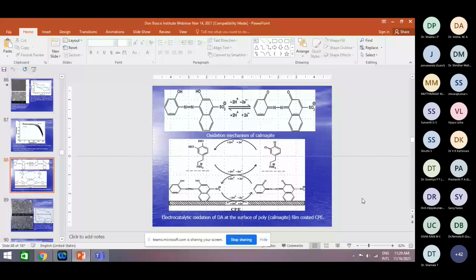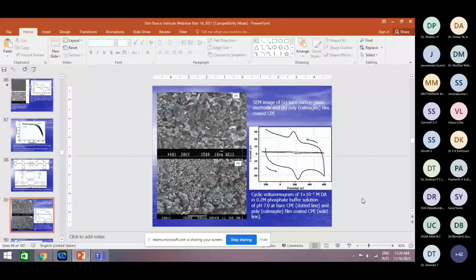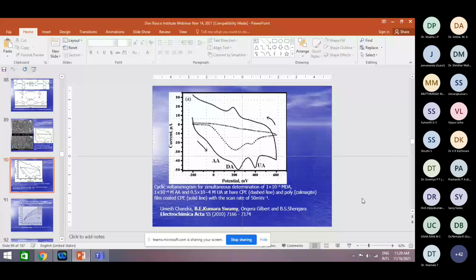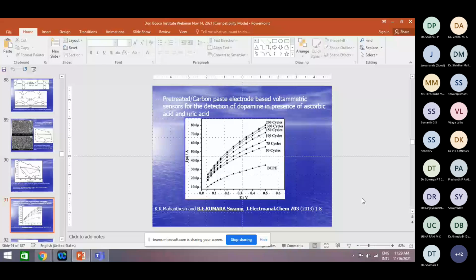You see, compared even with nanotubes or any metal oxides, we got a more than 7 to 8-fold increase in peak current using Calmagite, because of the electrochemical investigation, and we showed a very good difference in the ascorbic acid, dopamine and uric acid separation using simple methods. Then we did pre-treatment in the presence of NaOH for 50 cycles, 75 cycles, 100 cycles, 200 cycles. You can see we got very good sharp peaks.